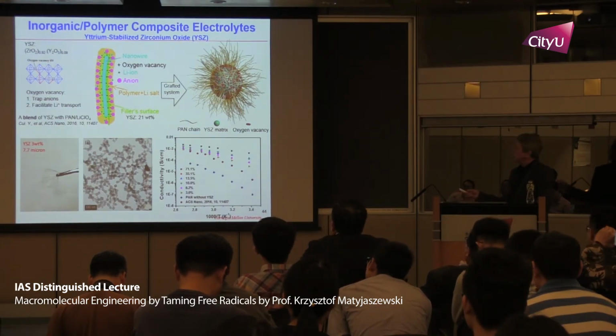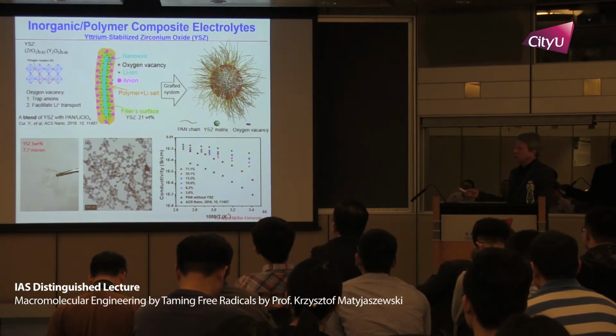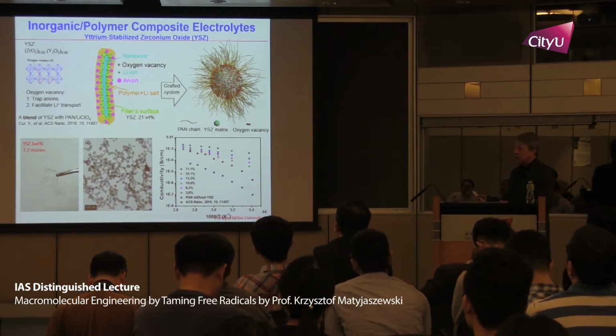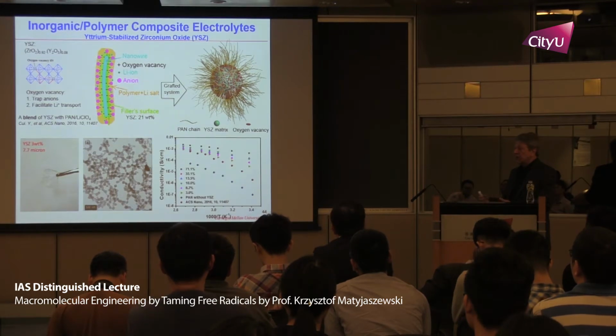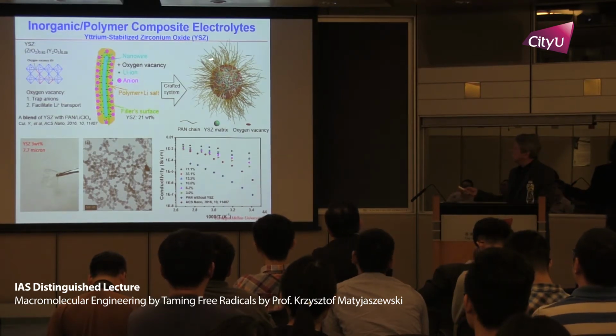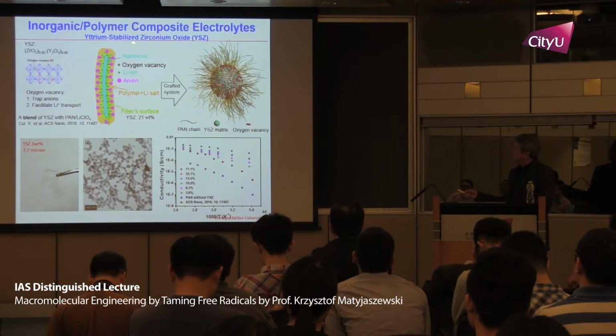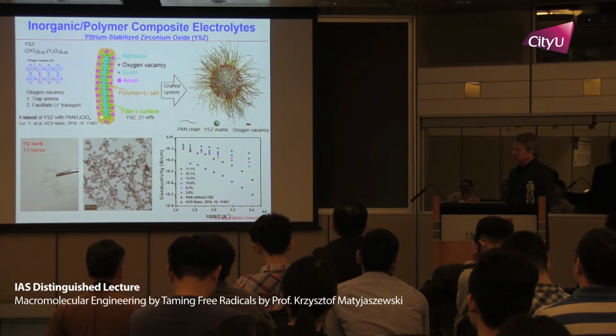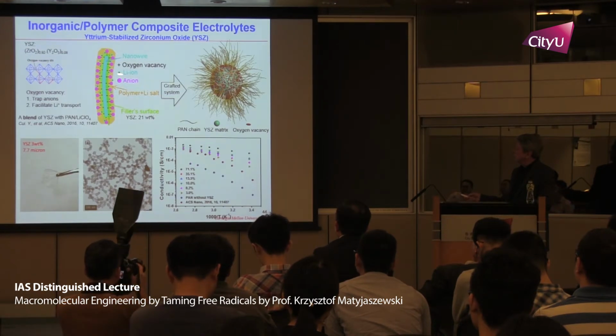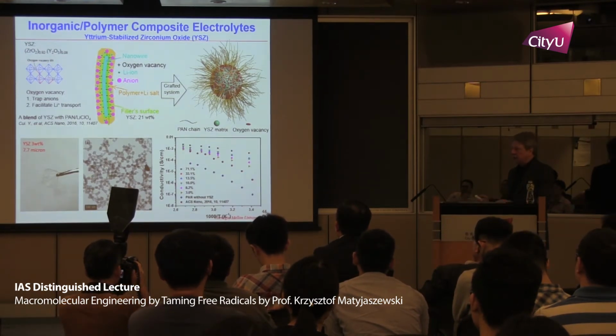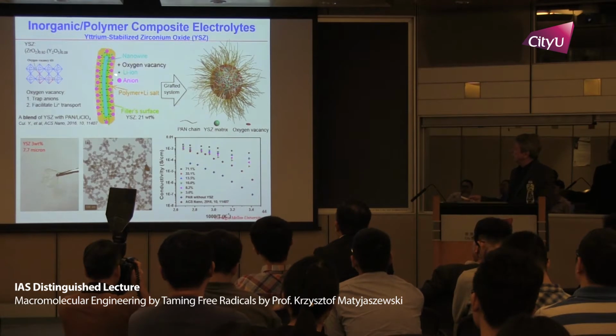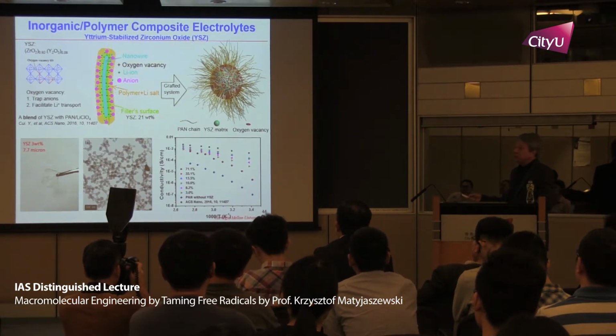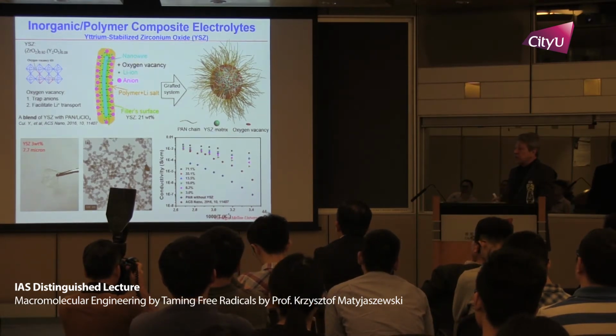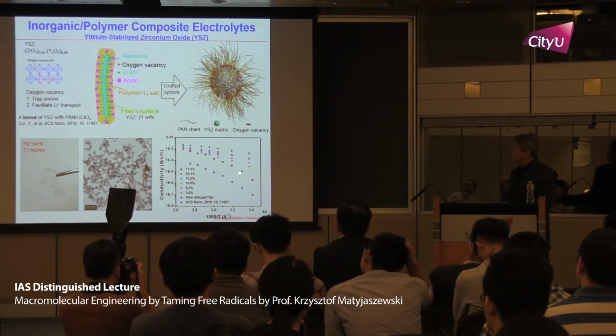There are some materials like yttrium stabilized zirconia or garnet materials and some others which have a very good conductivity, but in this particular case of YSZ, you have an oxygen vacancy on the outside. And in that case, they can absorb anions, so interact electrostatically with anions, and move lithium ions much faster. So first you have a transference number approaching unity, and also much higher conductivity.